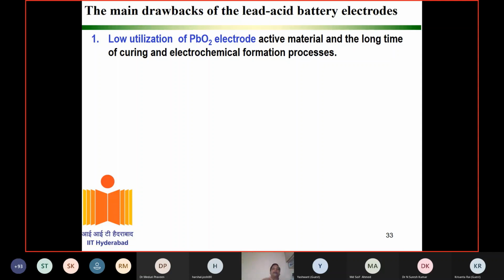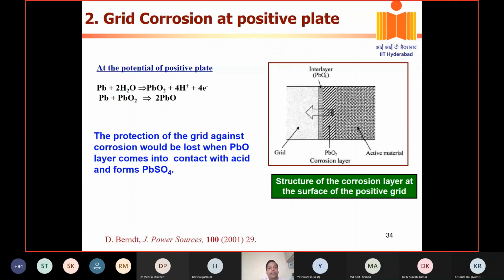Then you may get 70% efficiency. In the second cycle, you may get 90% efficiency. Then in the third cycle, you may get 98 or 99% efficiency. So a minimum of 3 cycles is required for the formation. We have developed processes where you can do the formation in 1 cycle. That's very, very important. This is one important area, the low utilization of active material. How can we improve the utilization of active material?